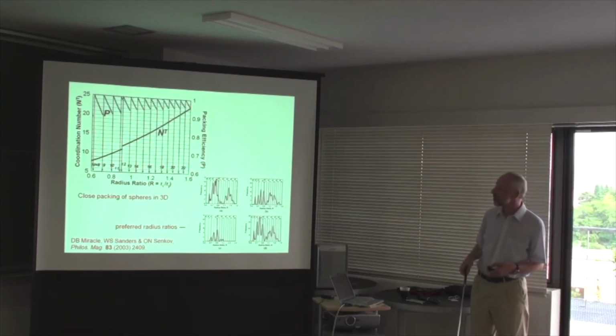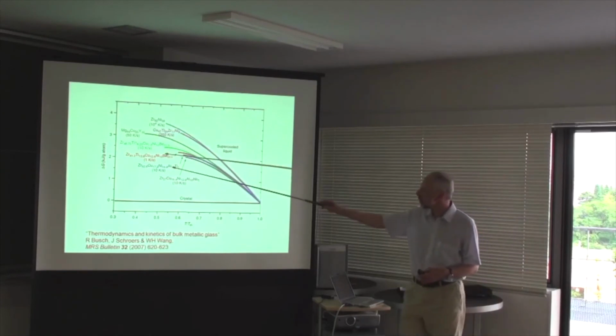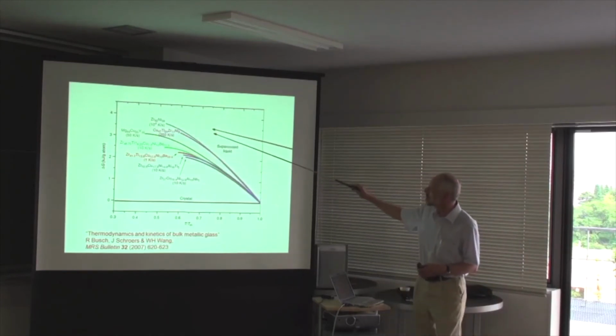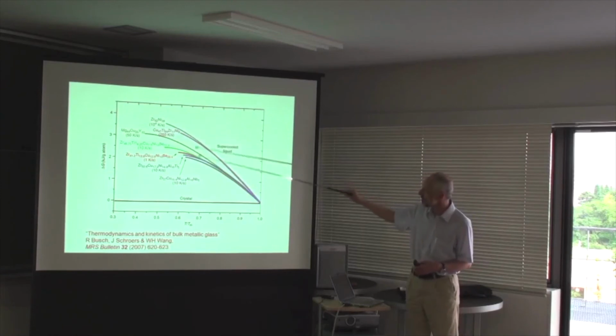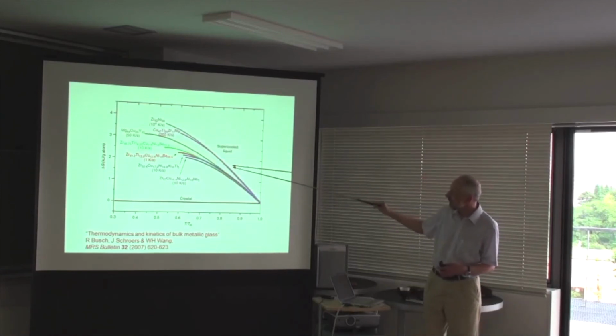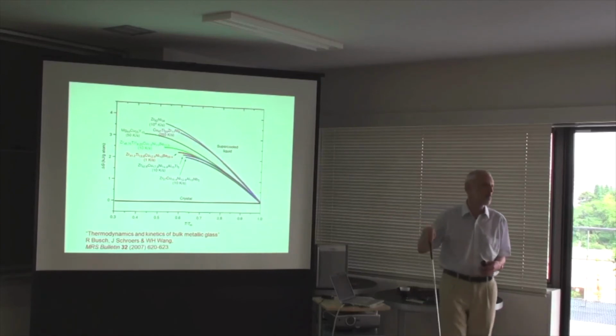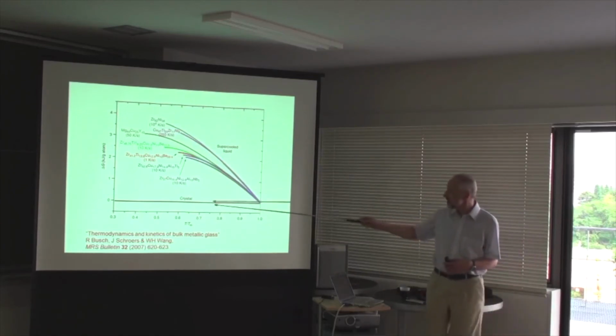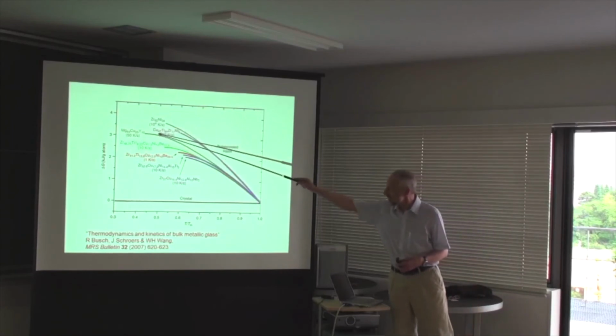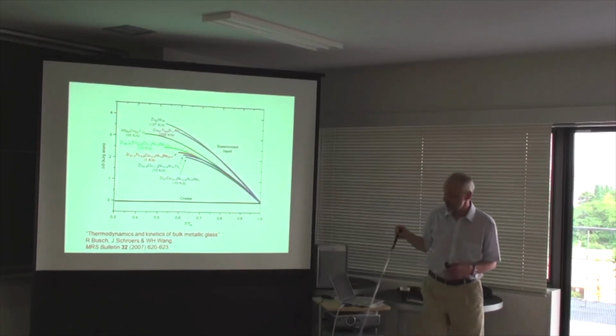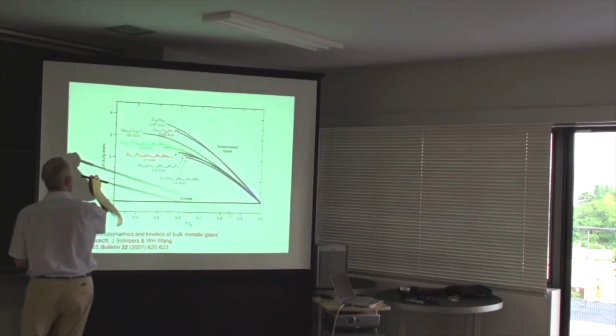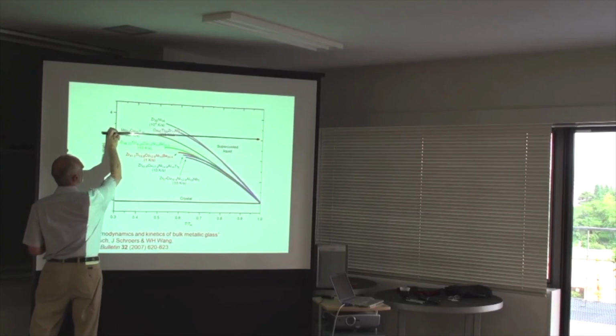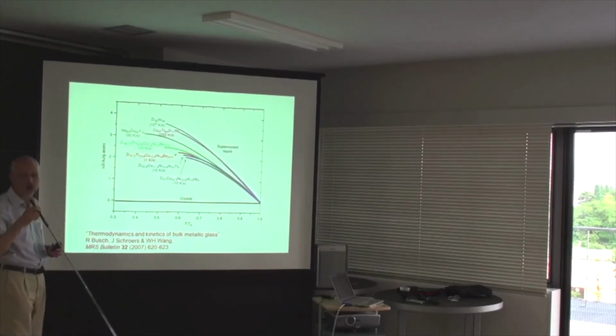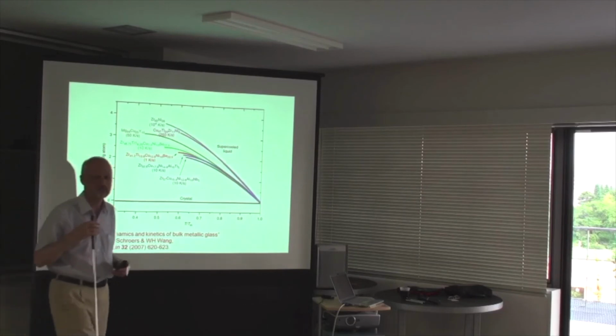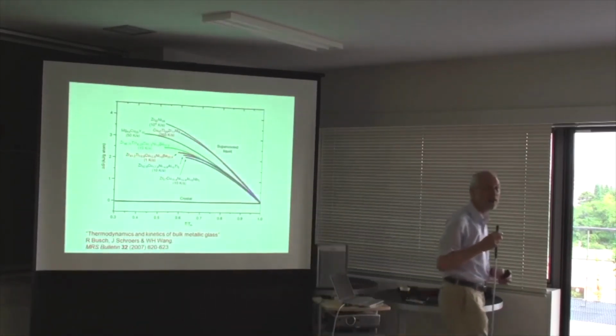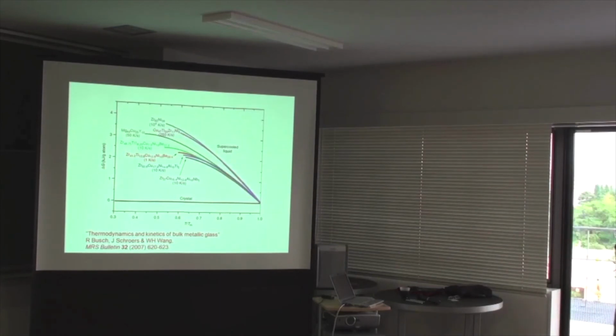But I want to really emphasize this point about order. Here's a plot of the free energy difference between these liquids which will form glasses and the crystal. And the gradient of a free energy with temperature is just the entropy. So this is saying that this delta G value here, related to the crystal, the gradient of this line here is essentially 0, which is saying there is 0 entropy difference between the glass and the crystal. In a remarkable result, thermodynamically. So they're really not disordered at all.